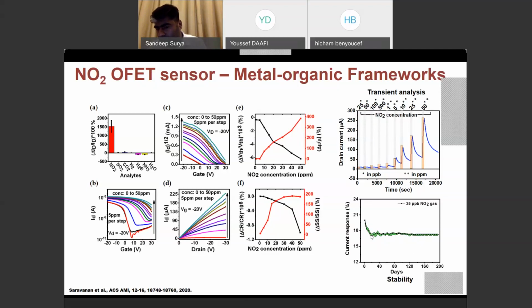With every 10 days gap, we did performance analysis of the device, and the device response seems to be quite stable over a period of 200 days, saying that this doesn't require any changes in the organic semiconductor in order to activate the surface.